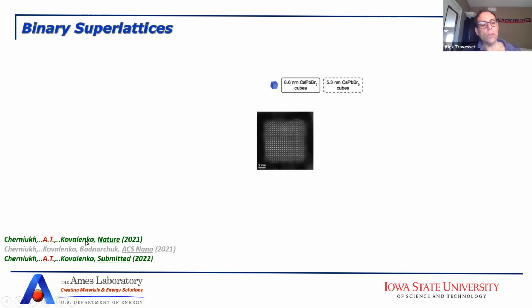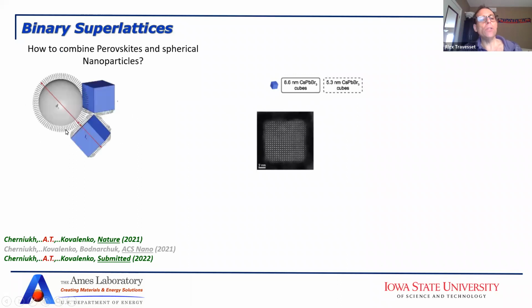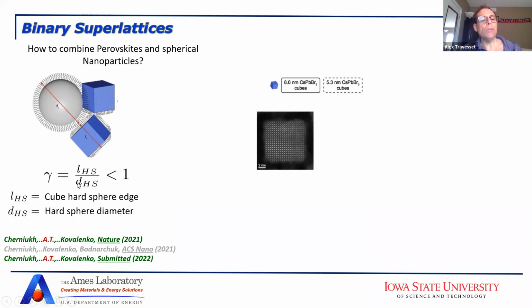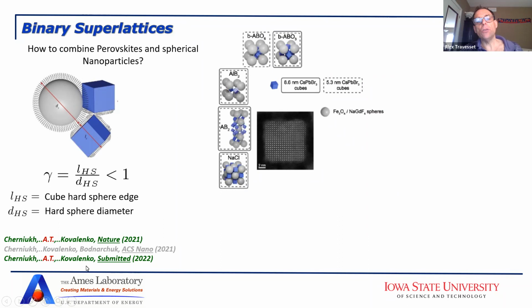This is work in collaboration with the group of Maxim Kovalenko. So when you have these 8.6 nanometer perovskite cubes or 5.3 nanometer cubes, and you combine them with spherical nanoparticles, something that looks like that, then you have a parameter, this gamma parameter, which is the equivalent of what you had for different types of binary spheres. And what you form is these phases: sodium chloride, AB2, AlB2, AB6, and b-ABO3. So you have many new phases where it's not just the position of the cubes, but also their relative orientation. And we have computed the packing fraction for all these, and I will come back to that.